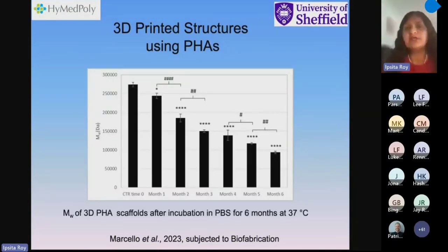In the body, we are using these scaffolds so that the cells can infiltrate and grow into the real tissue, and then this polymer disappears. So we looked at degradation, and indeed in 6 months, we observed that the MW value substantially decreased. And this is only in what is called phosphate buffer saline. If we really had conditions in the human body, I think it would be faster.